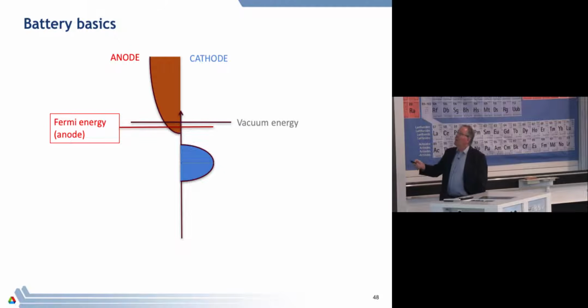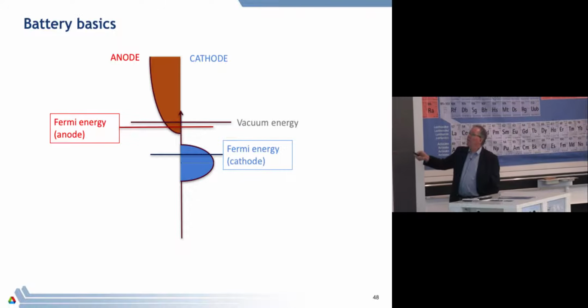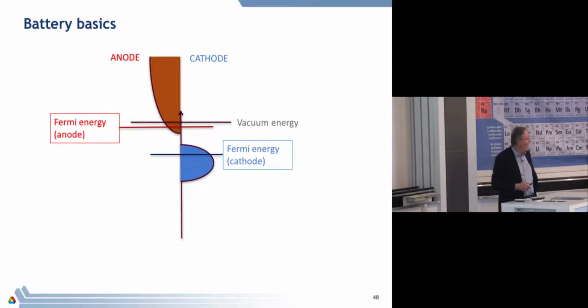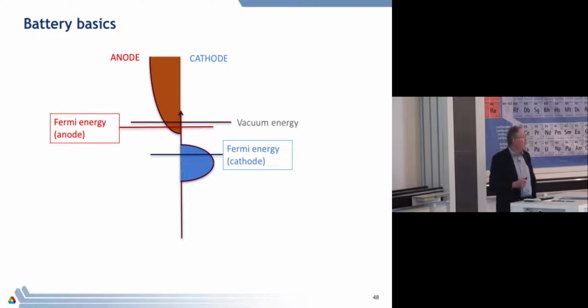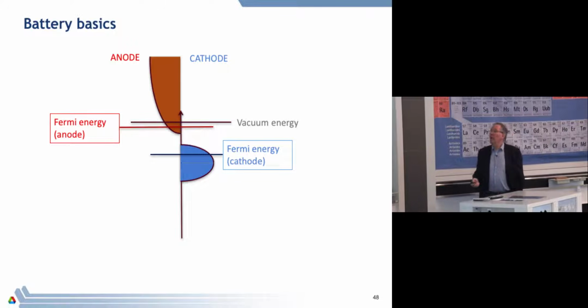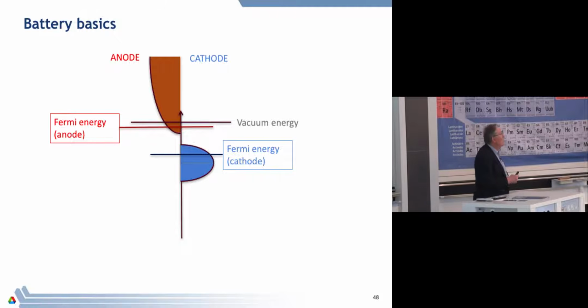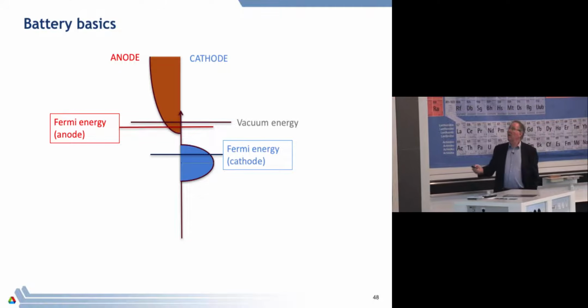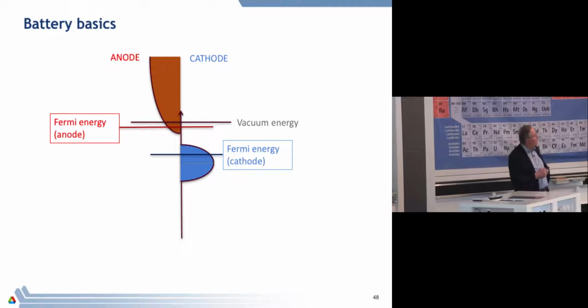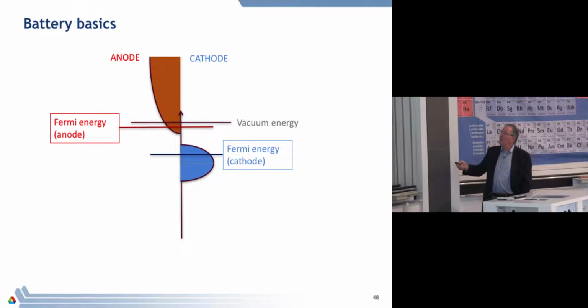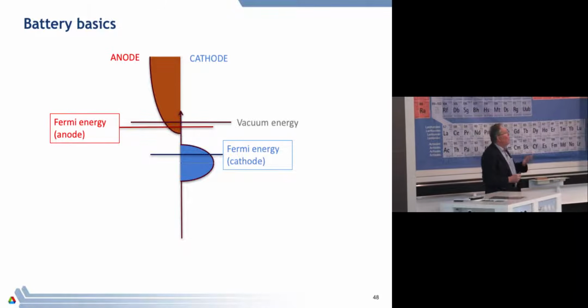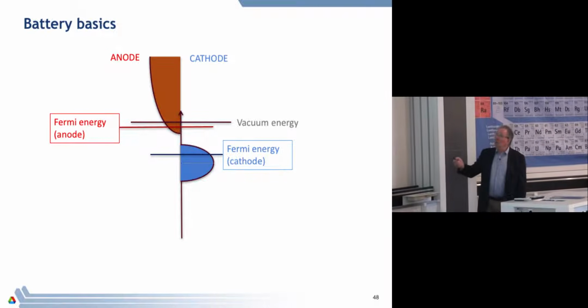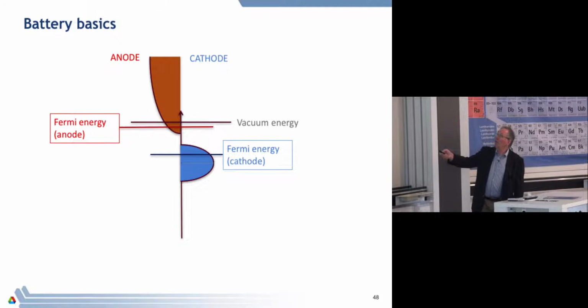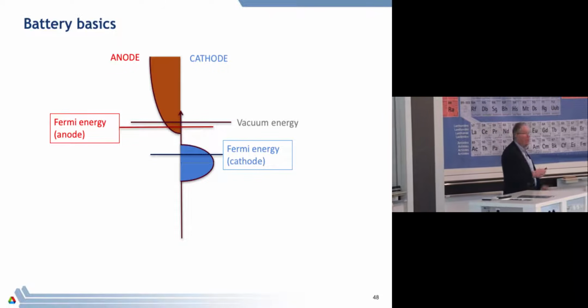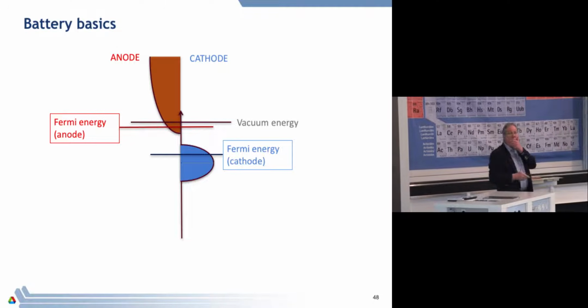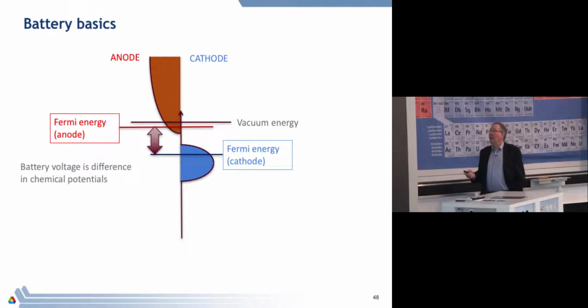So the voltage that you have in your battery is the difference between the Fermi energy in the anode and the Fermi energy in the cathode, because this will be the voltage that will be established in the external circuit. Okay? So if you now think about what I want to do to make a good battery, I would like to have this energy as big as possible. I would like to have the density of states in these two bands also to be as big as possible. Why does that matter? Well, that matters because the capacity of the battery, the number of electrons that I can take out from here and put back in there, is related to the integral of the density of states in the band, assuming how far I can move it up. Okay? So I want things with a big density of states